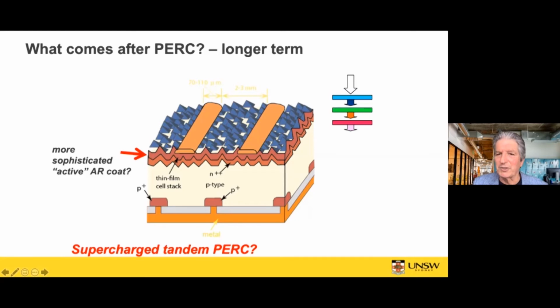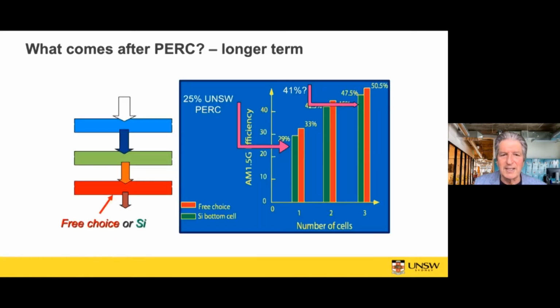But if you can stack cells of higher band gap onto a silicon cell, the uppermost cells can absorb the blue photons if they have a high band gap, and for lower energy photons they just look like glass, so those photons pass through to the next lowest band gap cell and so on. So you get this automatic filtering of the sunlight where the photons end up in the right cell automatically. So the high energy photons end up in the high band gap cell, which is able to convert them more efficiently than silicon can. So if you look at the limiting efficiency, this graph just shows this.